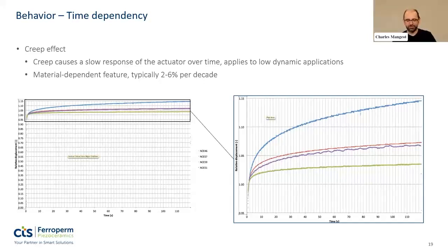Right, so in terms of frequency, what I wanted to say is that if you're performing cycles at, for example, very low frequency, you will see that the material has time to gain some creep effect. So first of all, you will see that the hysteresis curve is shifting a little bit because there's an average voltage which is not 0, so it will tend to shift the curve, and also some of this creep response is happening over time, so it will have an impact on the shape of the curve.